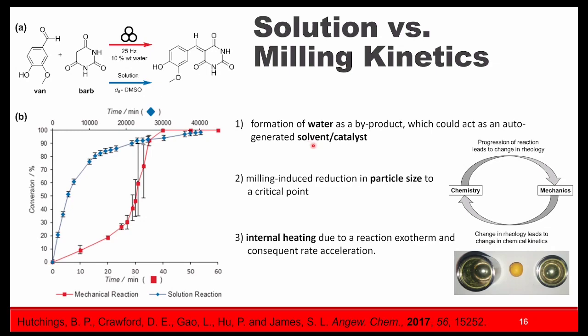They saw that isn't what caused it. They also said, well, maybe this is a particle size reduction effect. As you mill for a couple minutes, your particle sizes might be getting smaller, and so reactivity goes up over time. They pre-milled the reaction mixture, and they found no difference for small particle sizes. They basically pre-milled each reactant individually, mixed them together, and didn't see a change in kinetics. Or it could also be due to internal heating, in this case due to reaction exothermicity. Your reaction is releasing heat, and the heat is then driving the reaction, and that's why you see this acceleration over time. They changed the temperature, and they didn't see huge dependence on that.